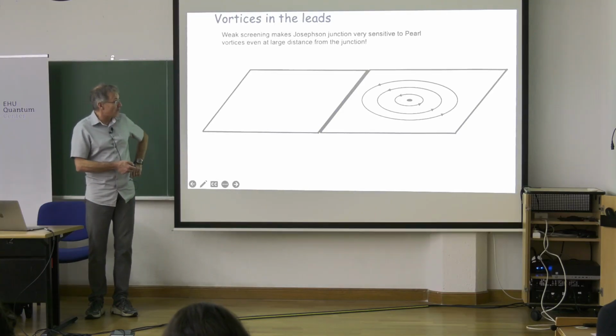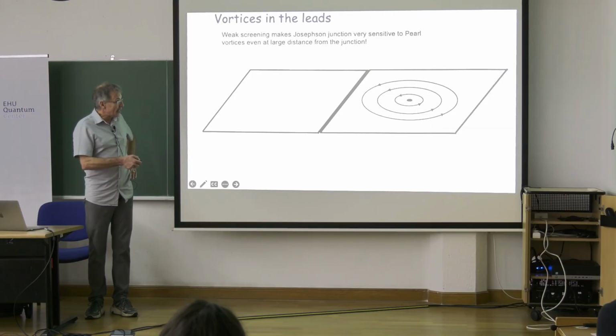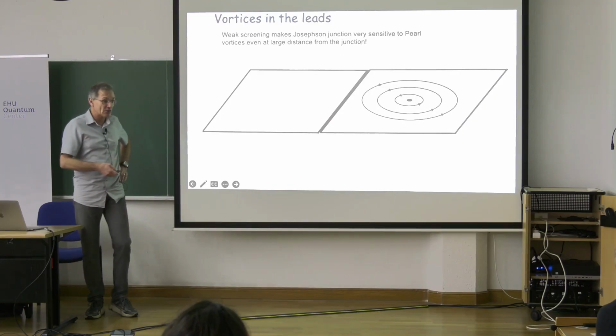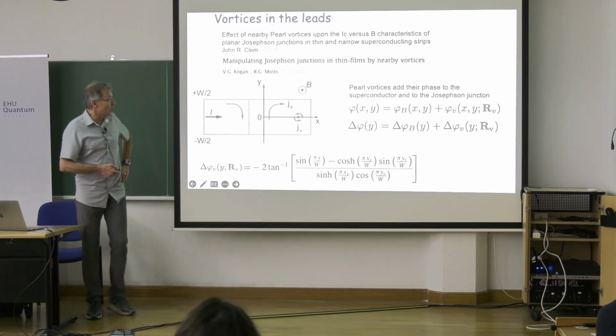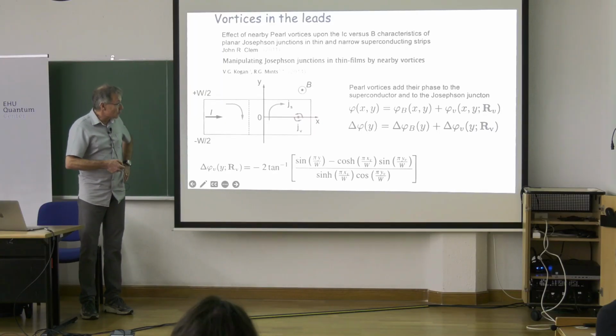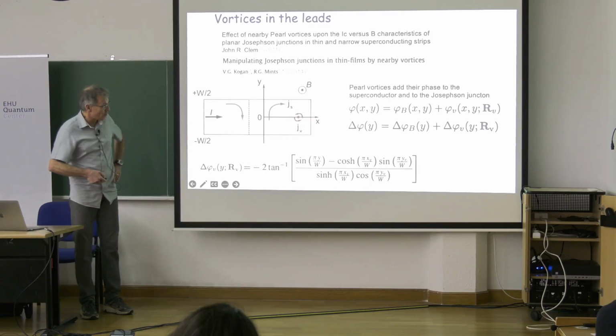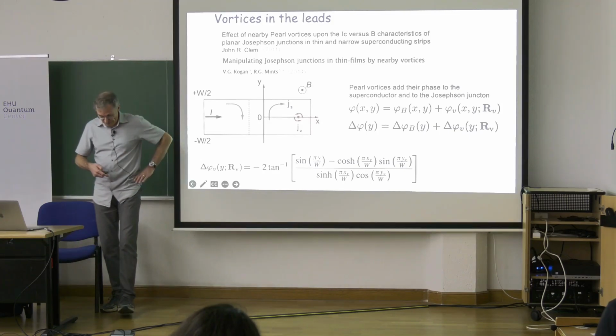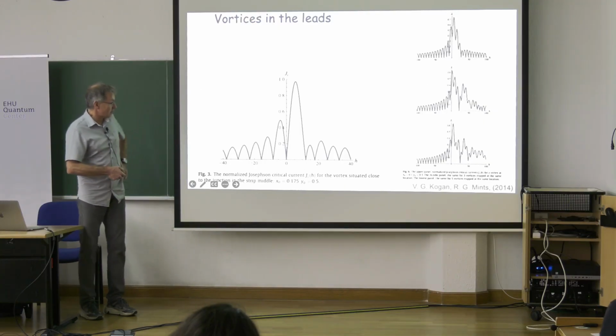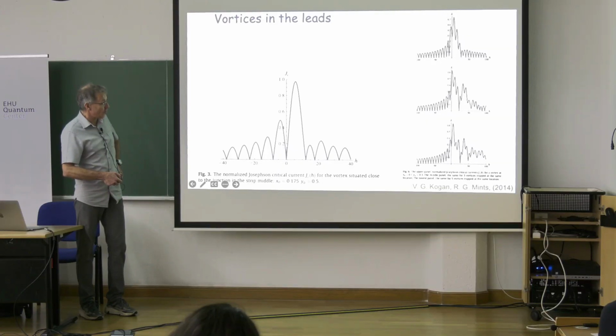So if you have a vortex in the leads, then because screening is poor, the current here modifies the Josephson phase and modifies the critical current of the Josephson junction. So to the phase shift produced by the magnetic field, we should add the phase shift produced by the vortex, which is given by this relatively complicated formula. For example, if you can place a vortex in a special position, such that at zero field it would be not a maximum of current, but a zero of critical current.